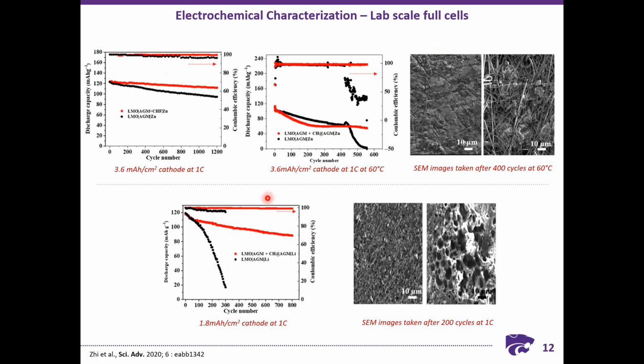And what they did next is they have actually prepared lab scale full cells. So previous ones were made with symmetric cells, so both the anode and the cathode were the same metal, while they have gone ahead to prepare full cells where the anode would be the metal, either lithium or zinc, while as the cathode they have used lithium manganese oxide. So all the full cells are limited by the cathode capacity. So at the lab scale level, they have used a cathode capacity of 3.6 milliamp hour per centimeter square, and they have cycled at a rate of 1C.